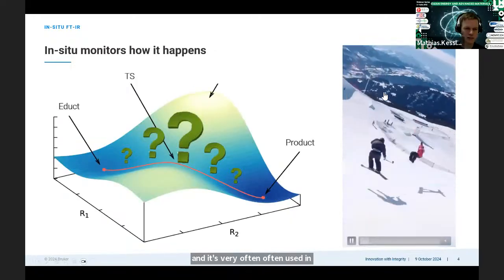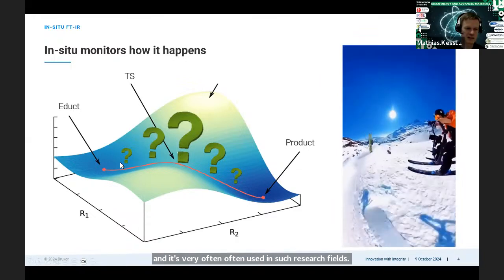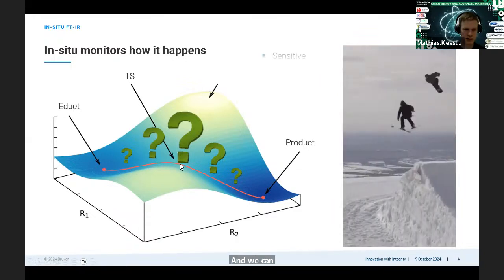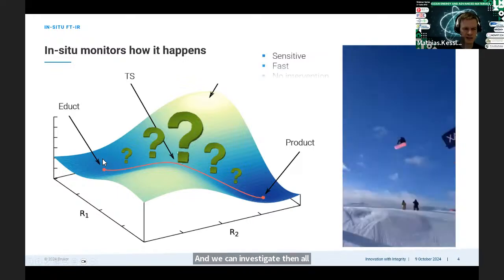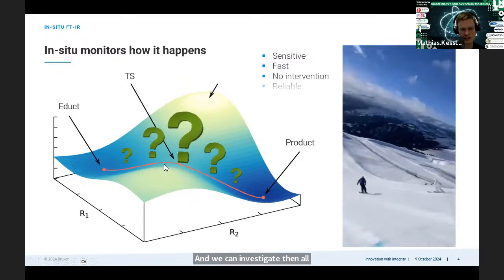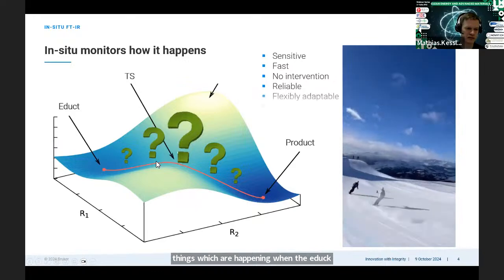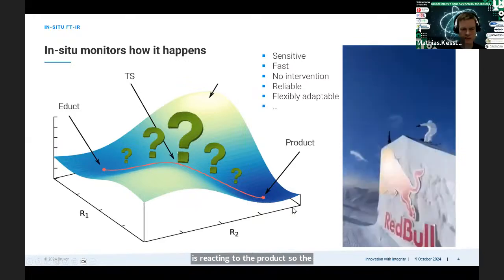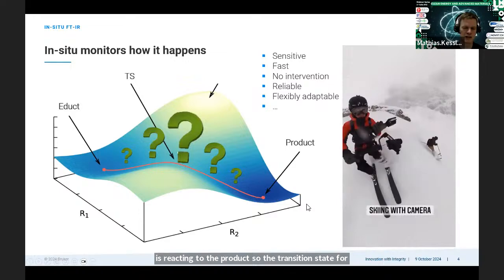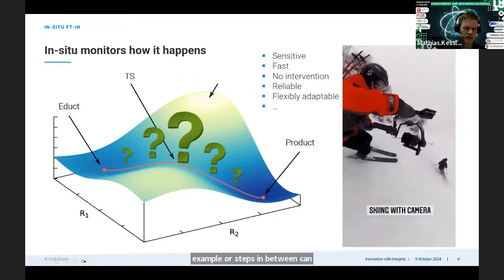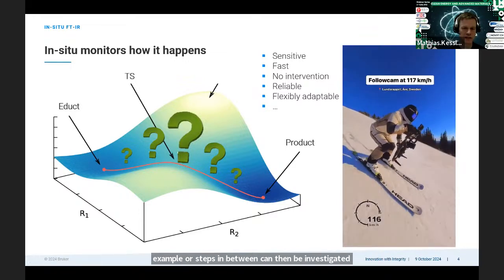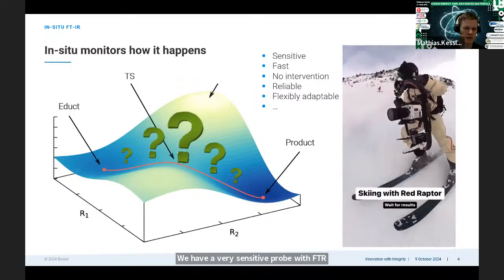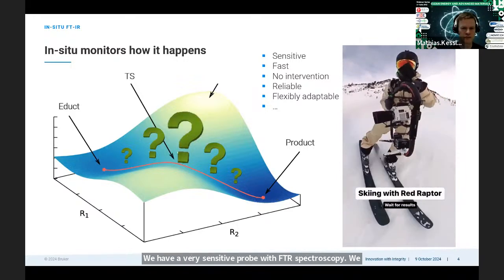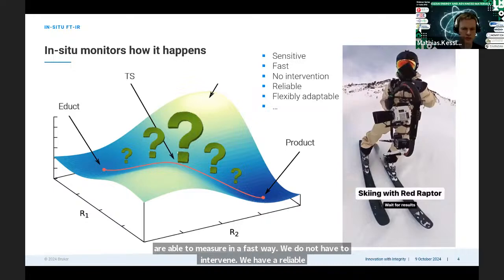And we can investigate all things which are happening when the educt is reacting to the product, so to the transition state, for example, or steps in between can then be investigated. We have a very sensitive probe with FTIR spectroscopy. We are able to measure in a fast way. We do not have to intervene. We have a reliable technique, and it's very easy to adapt that to the reaction.